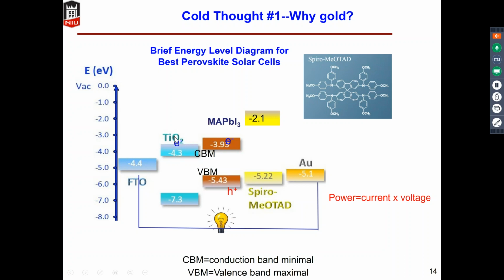So as the electron goes through the device and reaches the counter electrode side, which is the cathode side, you want to have the electron refill the holes in the valence band of the MAPbI3. However, think about the electrical power, which is the product of current and voltage. So you want both high current and high voltage. Here, if the electron is provided from a counter electrode with a lower work function, then the energy gap between here and here is all wasted, because this is the potential energy between the counter electrode and the VBM.